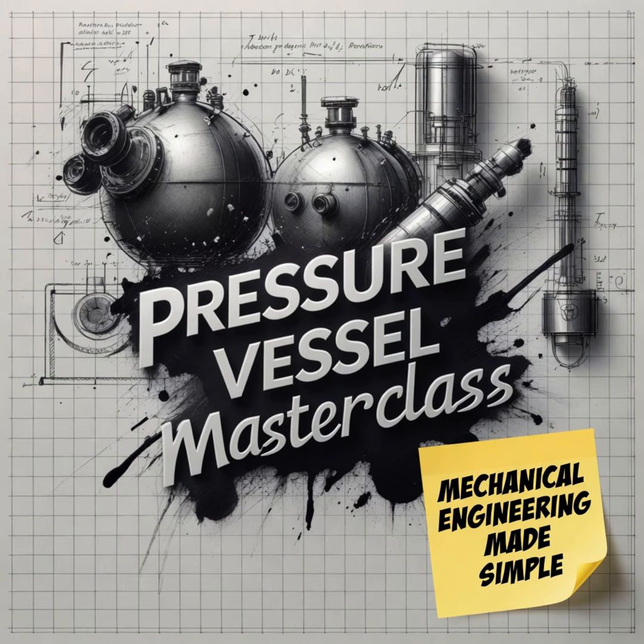Precisely. A vessel could fail from a vacuum collapse at a stress level that is phenomenally lower than the actual yield point of the steel. It stops being a question of how strong is the steel and suddenly becomes a question of how stiff is the shape. Wow. And unlike a tension failure, which might start as a slow leak or a visible bulge, elastic instability failures happen suddenly, without warning, by the catastrophic, instantaneous crushing of the component. It literally happens in the blink of an eye.